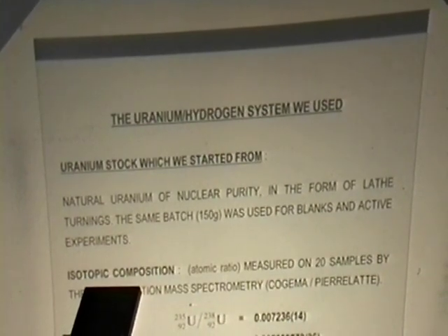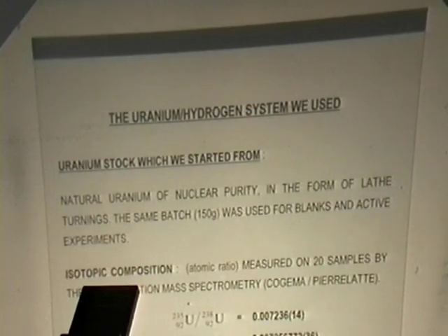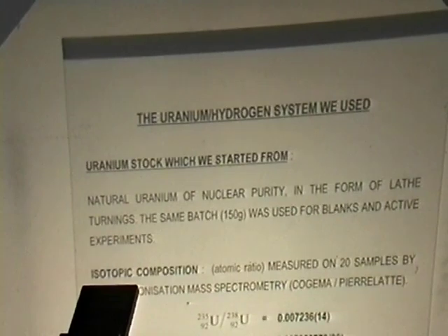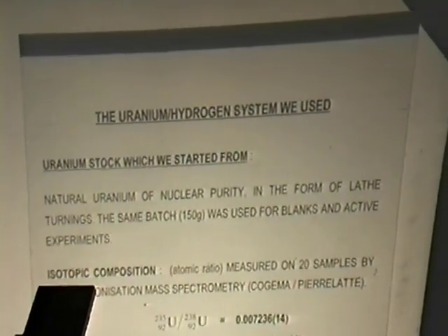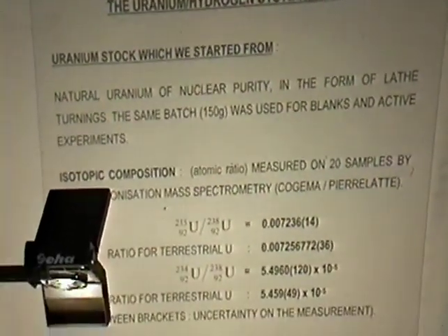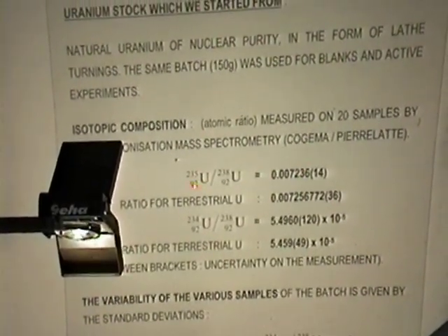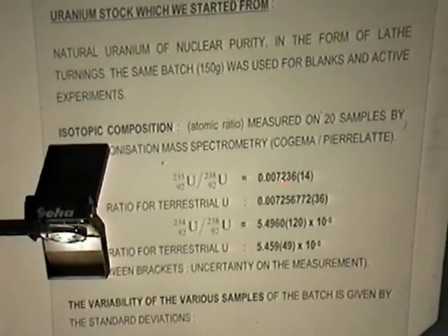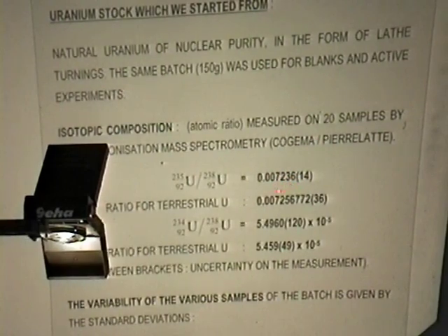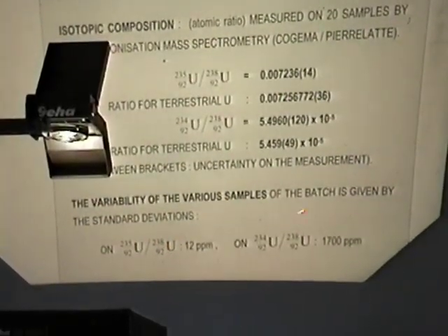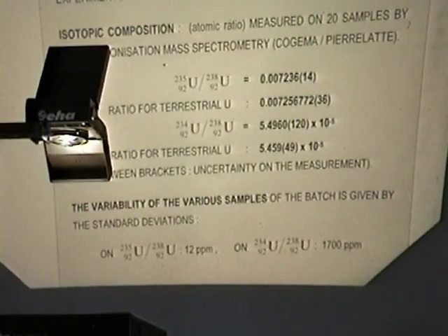For the hydrogen uranium system we are using, we start from very pure uranium of nuclear purity, which has been given to us by Cogema, with this isotopic composition. You can see that we have characterized the uranium by its ratio 235 to 238, which is a very common measurement used by nuclear people. This is the uncertainty on this ratio, and the figure you see here is the ratios for terrestrial uranium. You can see the variability of our samples because we have used the same batch of uranium for the whole experiment, 150 grams, and we have analyzed more than 20 blank samples. So this is the uranium system we use.